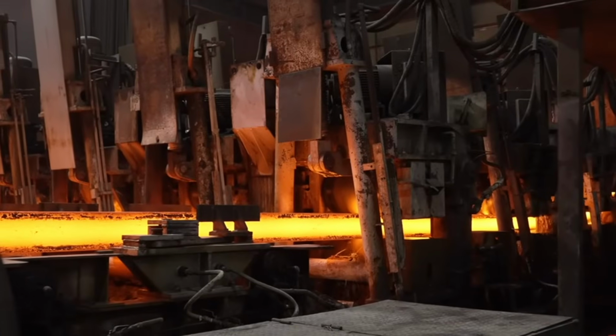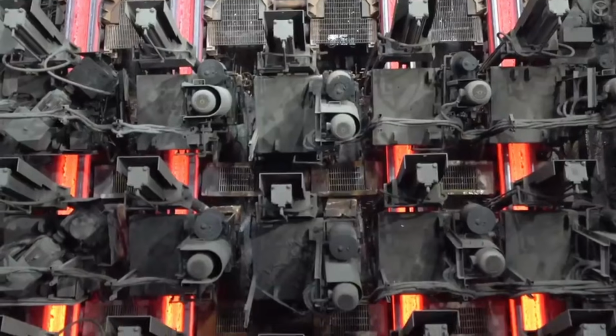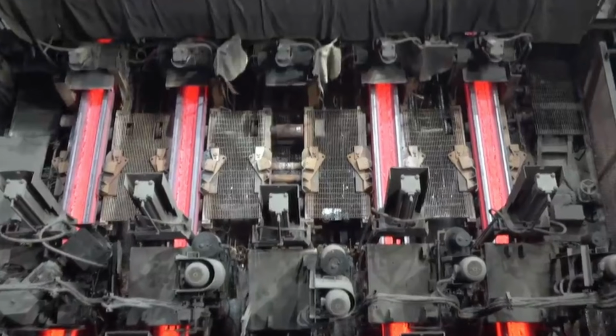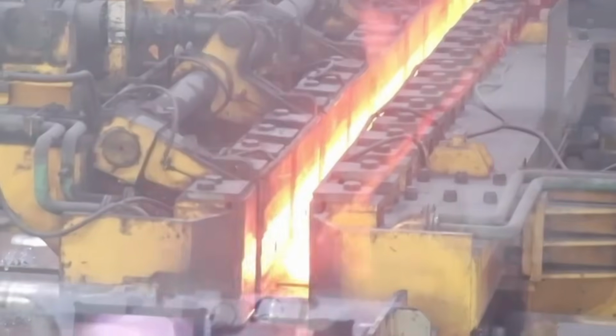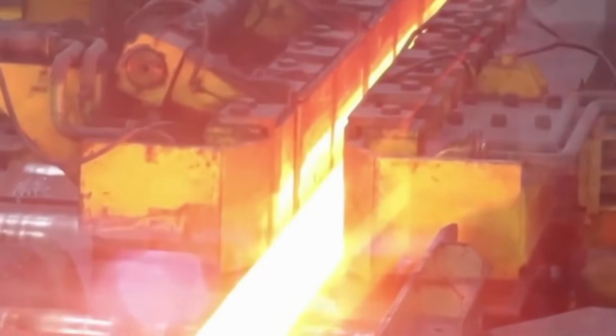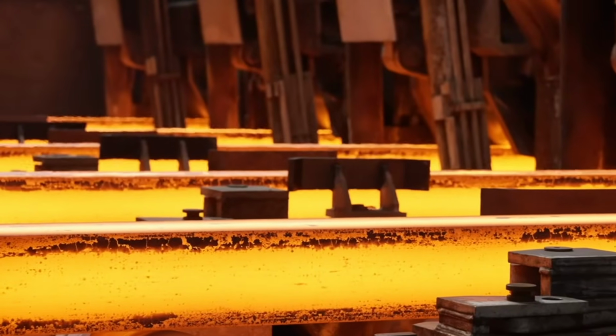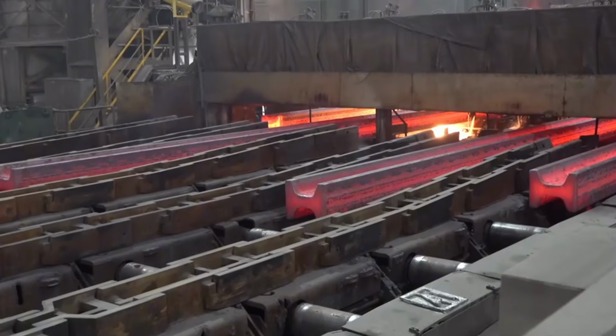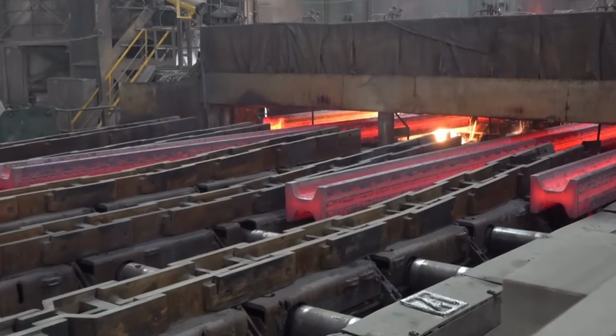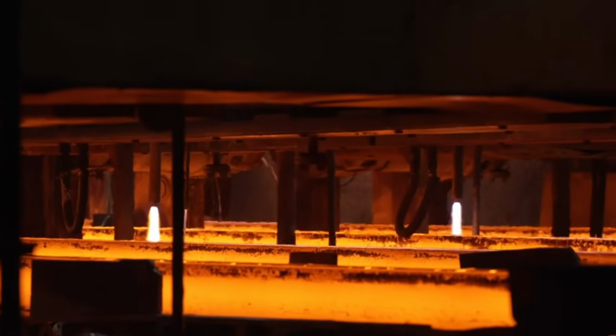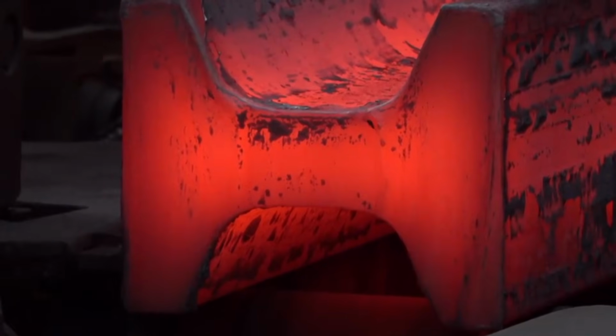Temperature control during rolling is critical. Steel must stay hot enough to deform without cracking, but cool enough to hold shape. Water sprays between stands wash away scale and control temperature, creating massive steam clouds. By the final stand, the beam cools to around 1,500 degrees, still glowing red, but solid enough to maintain its I shape.